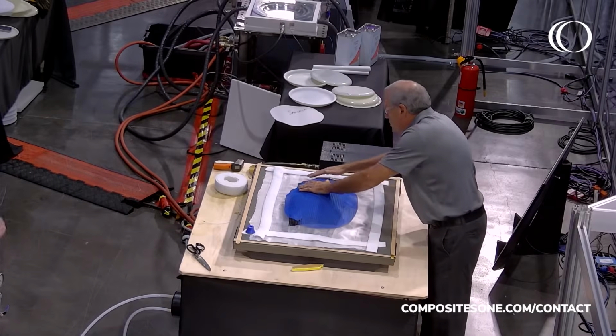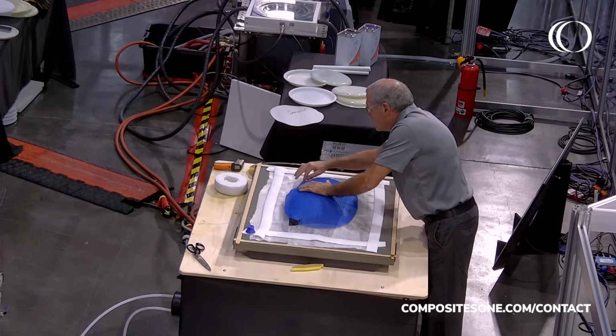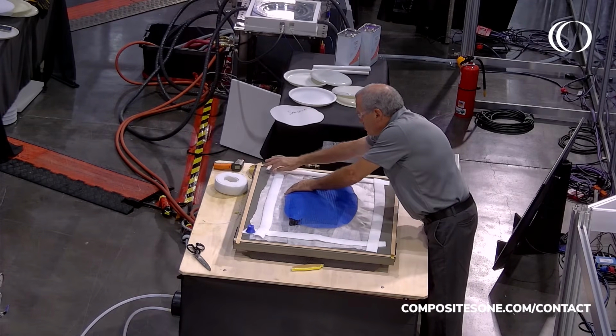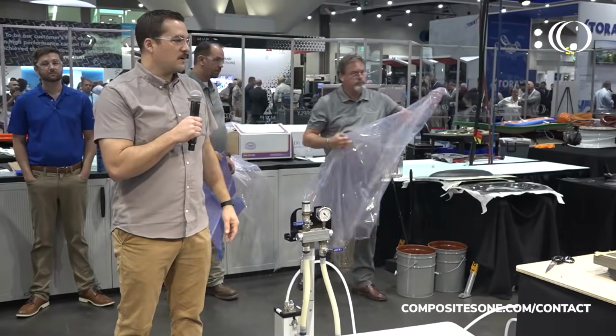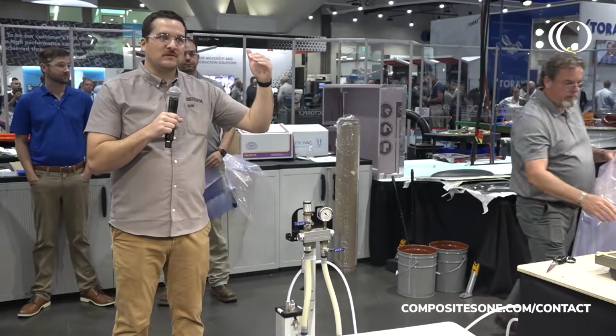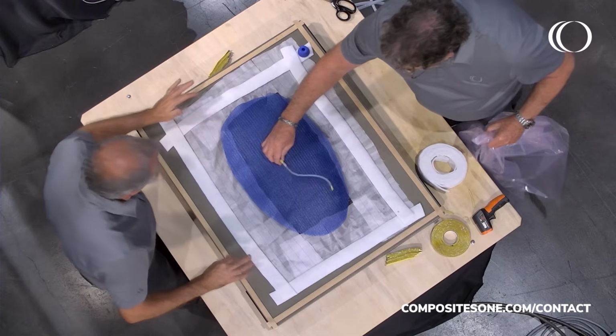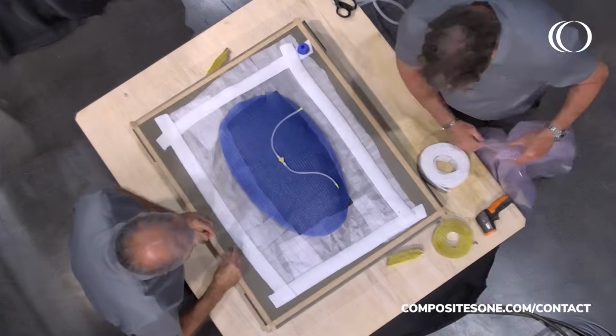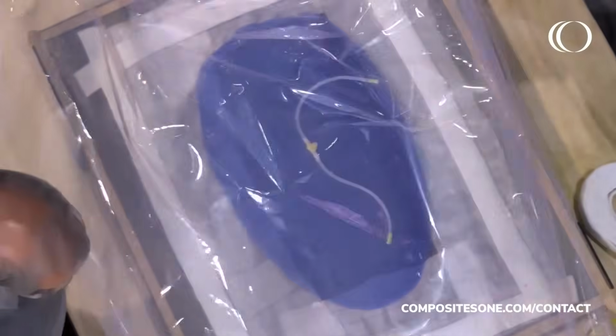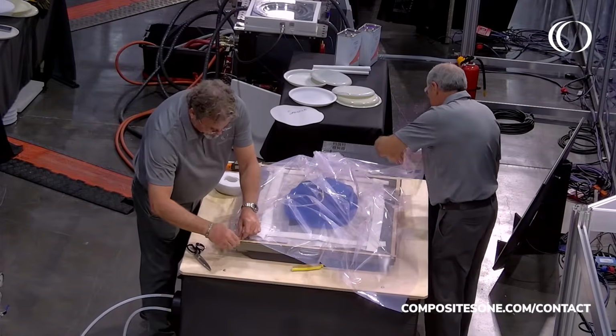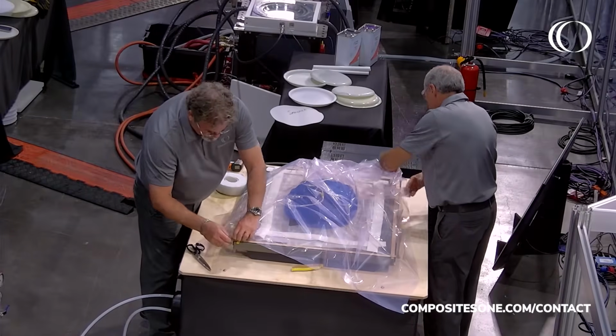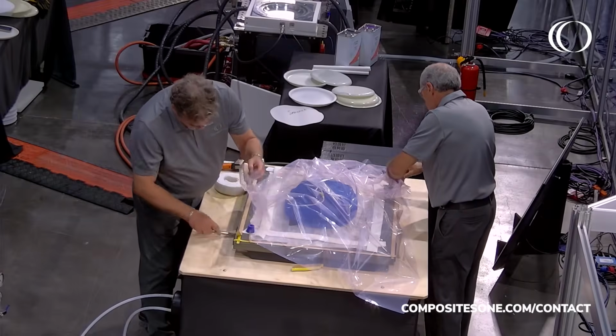As James mentioned, you're able to heat the tool at a very controlled ramp. You're able to maintain temperature thresholds if you want to dwell. That can be programmed into the machine. You can have TC feedback into the system as well. And then you can also reach your final temperatures quickly. Once the part is cured, you're able to dump that temperature by using the cooling circuit, which is basically just a reverse flow. Then you're able to cool the tool very quickly and cycle your part. From that point on, you're able to repeat the process, fine-tune it, and really work a significant amount of cycle time out of the process.